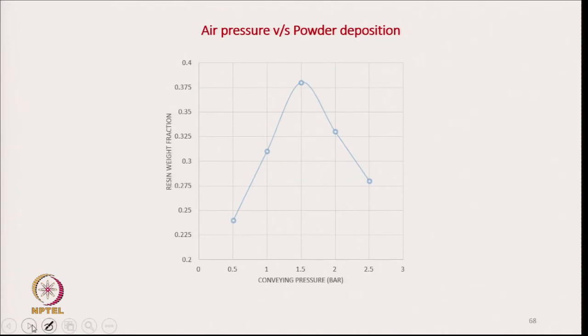The next experiment is the effect of conveying air pressure on powder deposition. Here we can see as we increase the conveying air pressure from 0.5 to 1.5, there is a sharp increase in the resin deposition. But once it is more than 1.5 bar, there is a sudden drop in the powder deposition.